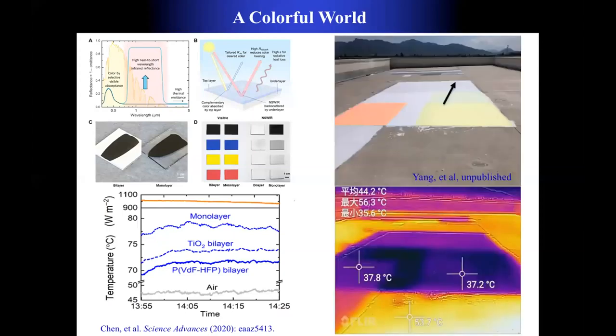And this is one material we made, actually a coating, and you can see we can have different colors. We applied it on concrete, and the temperature difference on the concrete is about 20 degrees C. So those materials have been made, and as far as I can tell, there are about 200 different papers on making or just measuring different materials for radiative cooling properties. Some have pretty good properties, some not, and some just have something that looks interesting to publish a paper.